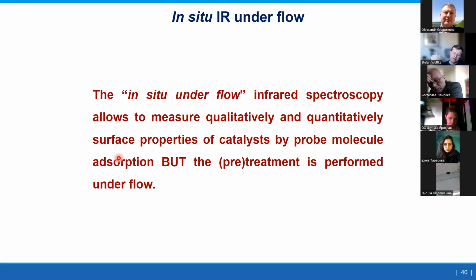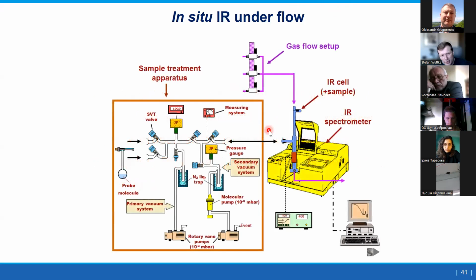And then the next step of in situ IR spectroscopy is to do it under flow, in order to have more dynamic insight and study quantitative and qualitative dynamic properties of the catalyst. And here's the same setup that I showed you before, but you just have gas flow on this. So here's the sample, and you can have gas flow and can activate or play with the sample. And I will tell you in a moment what we did.